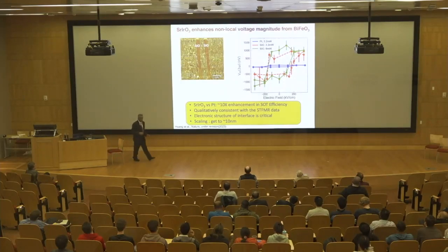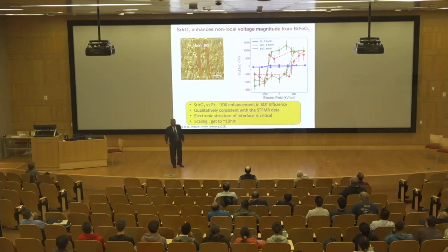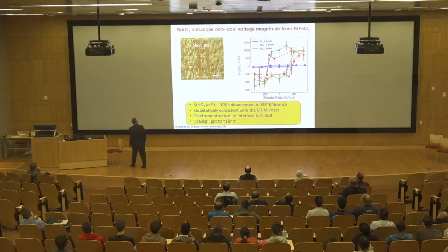What we then showed was, if I replace platinum with our oxide material, this is strontium iridium oxide, it's a topological insulator material, our output voltage goes up by about 20 times. We go from 50 to 100 nanovolts to now microvolts. Okay? And these are two different measurements for this. And it's qualitatively consistent in multiple measurements.